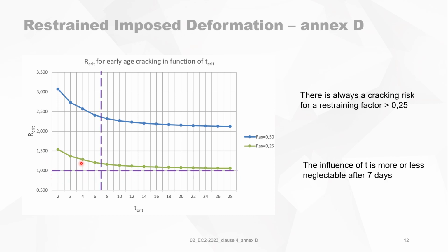We also see that, for instance, for a restraint factor of 0.5, after 7 days the influence of time in the formula is more or less negligible.